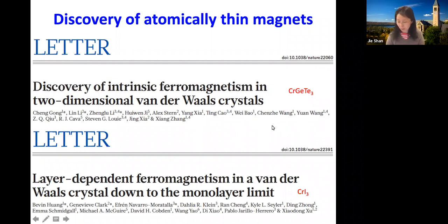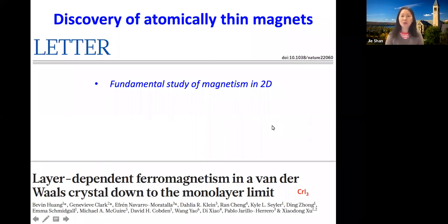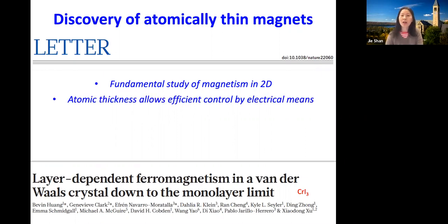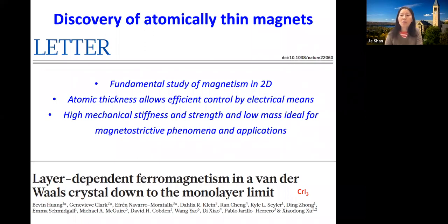down to the monolayer limit. What's remarkable about those new discoveries is that now we have two-dimensional crystal materials, which allow fundamental study of magnetism in the true 2D limit. The atomic thickness allows very efficient control of magnetic states by electrical means. You can put them into a capacitor-like structure, apply a large field, or use electrostatic techniques to introduce large doping density. The high mechanical stiffness and strength and low mass of these materials are ideal for magnetostrictive phenomena and applications. I hope I'll be able to give you some examples along those lines.